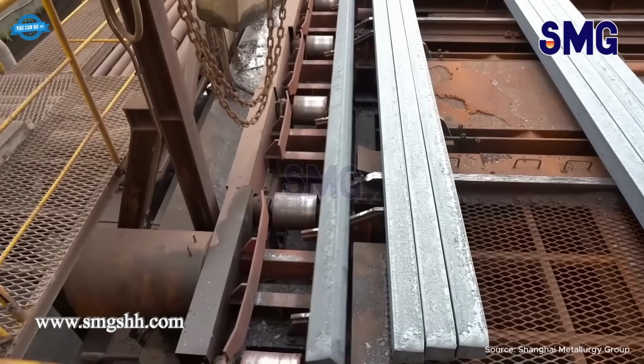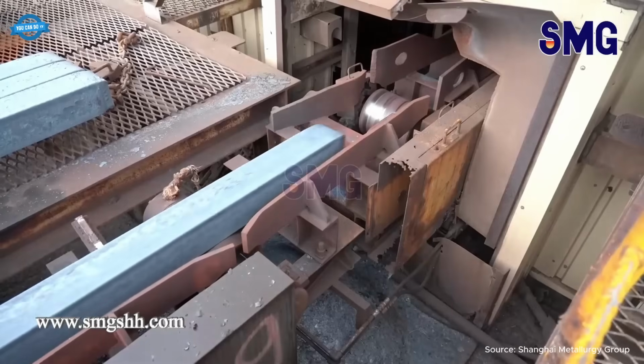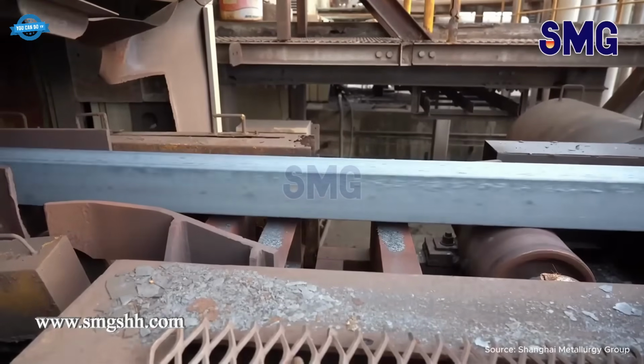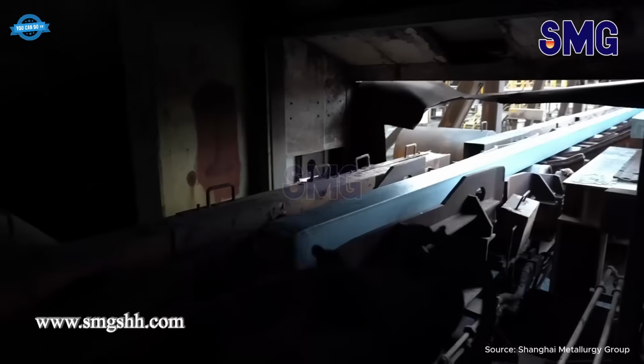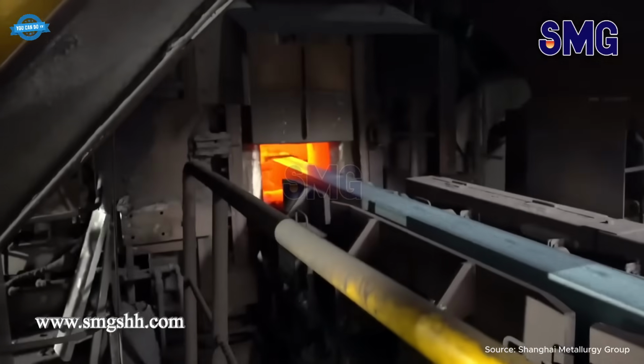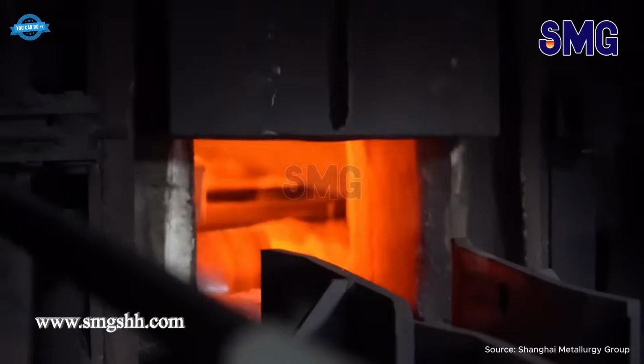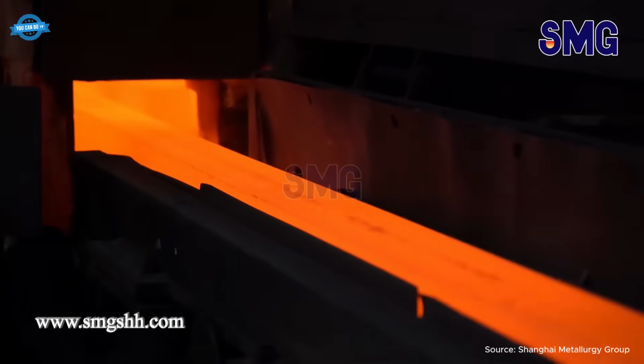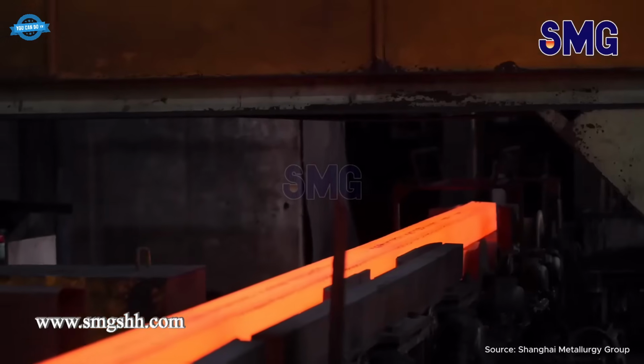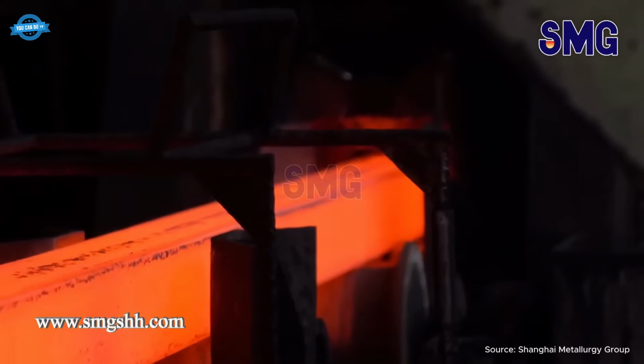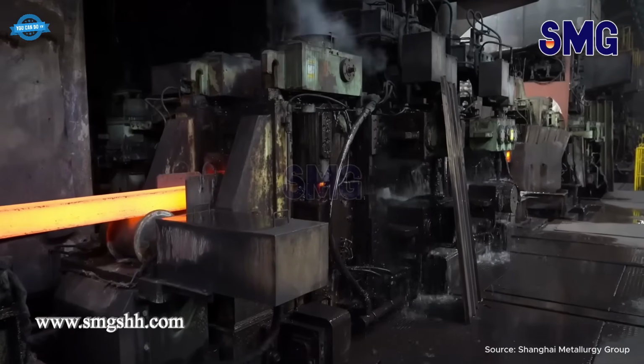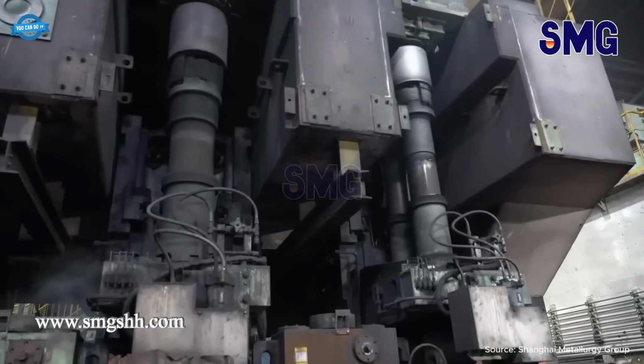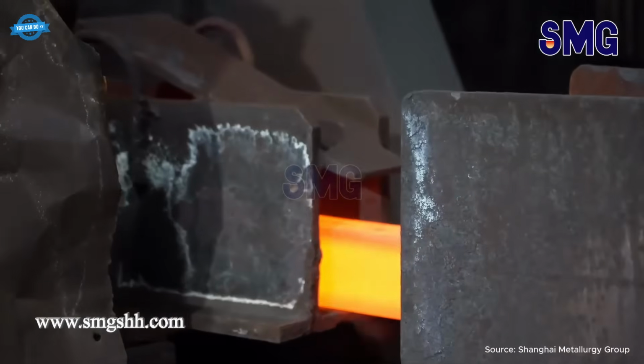The smooth long product, rebar production line at Shanghai Metallurgy Group integrates advanced automation and metallurgical precision. Billets are uniformly heated in high-efficiency furnaces, reaching 1100 to 1250 degrees Celsius to ensure proper plasticity. They then enter a multi-stand continuous rolling mill, where controlled deformation shapes them into precise diameters with embedded ribs.